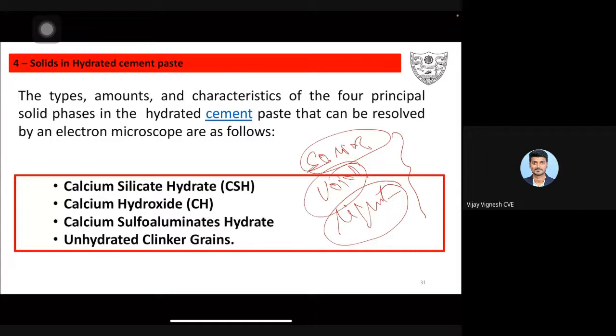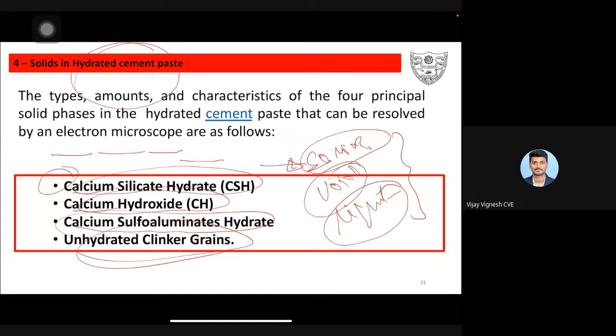For the time constraint, I want to talk about only what solid compounds are present in the hydrated cement paste. Initially we start with raw material, after that the clinkering reaction, then the cement microstructure, now the hydrated cement paste microstructure. So what are the four solids present here? Calcium silicate hydrates, calcium hydroxide, calcium sulfoaluminate hydrates, unhydrated clinker grains. These are the four solids present inside the hydrated cement paste.